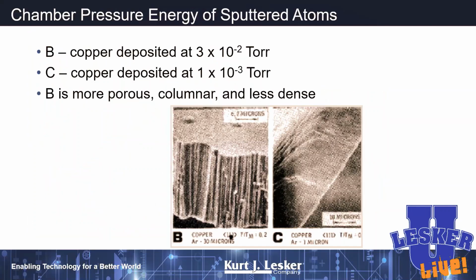And here's some examples. These are both copper. Over here we have copper at 10 to the minus 2 torr, and you can see it's very columnar, not very dense, not a great film example. Then if we go down a decade in pressure, the mean free path is increased substantially. Now we make essentially an amorphous, dense film. The arriving atoms have much more energy. They can move around and fill in spaces and actually make a great film.